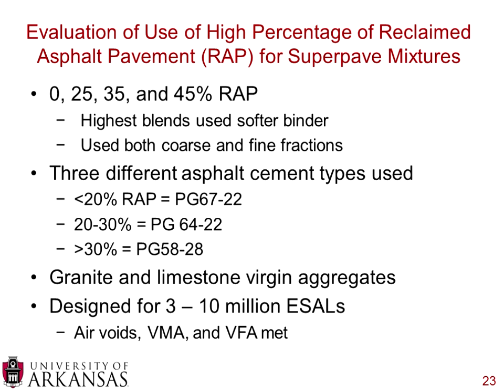The next study, this is the study that was done in Florida. They used 4 different levels of RAP, 0, 25, 35, and 45% RAP. And the highest blend, the 45% RAP, they used a softer binder. You can see that for the two highest blends, they used a softer binder. And they used both coarse and fine fractions of the RAP. So down in Florida, they used different stockpiles, one which had been further crushed. So they had a coarser fraction and a finer fraction of RAP.